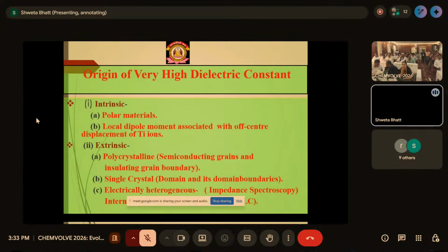There are two factors: the intrinsic factor and the extrinsic factor. Intrinsic means there is a local dipole moment associated with the Ti ions, and sometimes it is a polar material. The other one is the extrinsic factor. Later on, I will discuss the polycrystalline, because one of the most probable theories for the high dielectric constant of CCTO is polycrystalline, semiconducting grains and insulating grain boundaries. I will discuss this on the next slide. And there are single crystal domains and their domain boundaries. These are a few reasons how this material possesses a high dielectric constant.